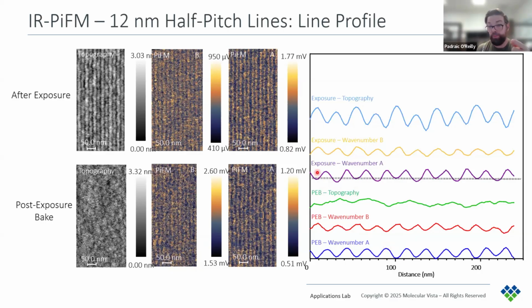And secondly, the purple line here, which is highlighting the exposed parts of the exposure-only sample, shows this sort of double line artifact. So you can see that every second dip is shallower than the previous. You can also see this to an extent in the post-exposure bake sample, so this blue line, but it's less pronounced. And in fact, this artifact is carried all the way through to the developed sample.